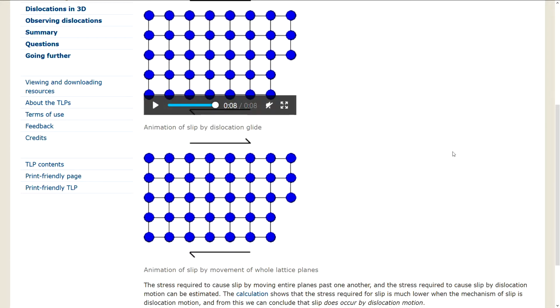So you can see here the end result is the same. It's just a matter that in the bottom one, where the whole plane has to slip, the problem is you have to break all the bonds at the same time, requiring a lot of force, a lot of energy. But if there's a dislocation, then you only need to displace 1 row, 1 bond at a time.